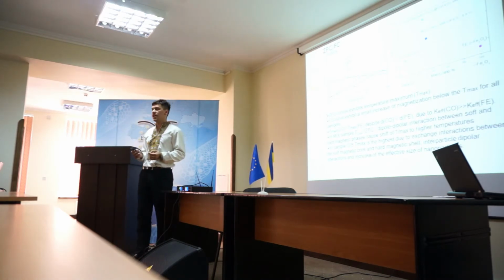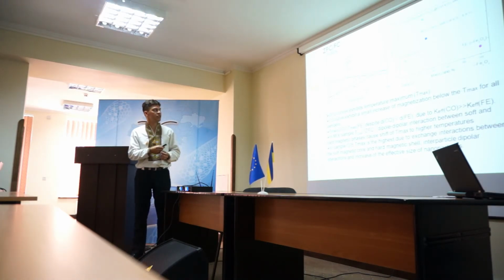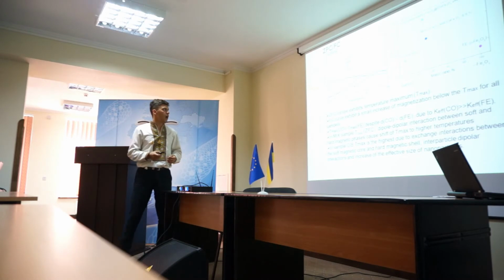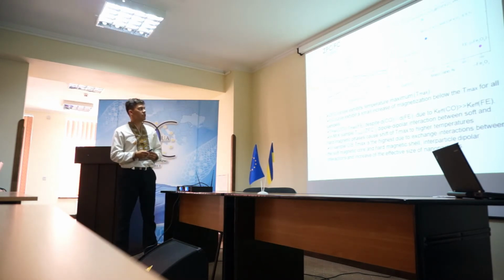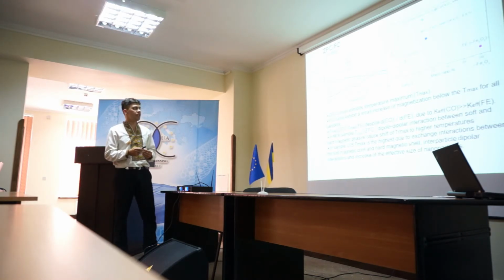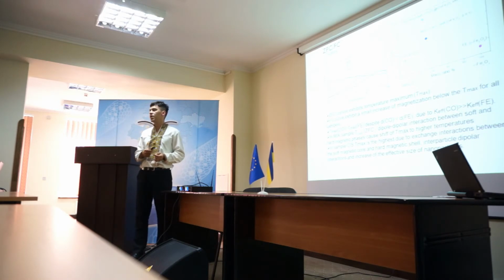To investigate the temperature magnetization dependencies of these samples, we use a simple procedure, the so-called zero field cooling and field cooling cycles. For the samples, we have a maximum on the ZFC, and we have temperature irreversibility, after which at lower temperatures the branches are separated. This behavior is typical for single domain nanoparticles.